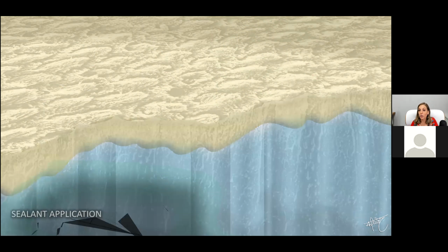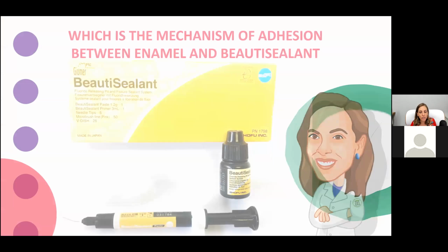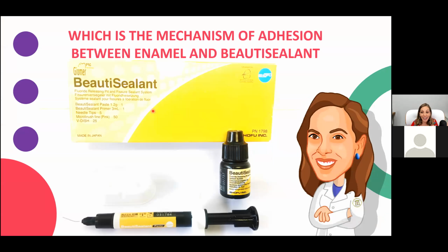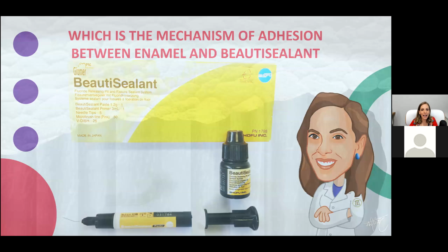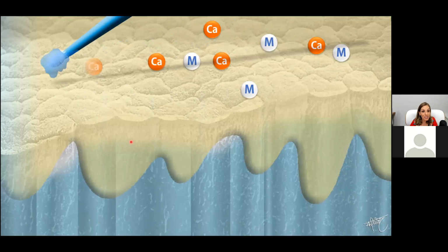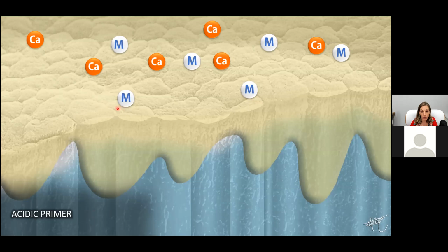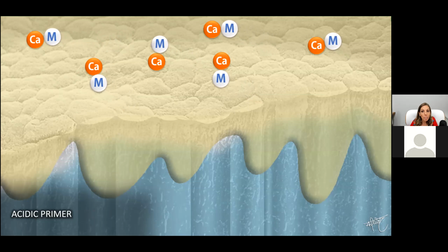And again, you are asking me, which is the mechanism of adhesion between enamel and BeautiSealant? And this was the question that I made to Mr. Giomer. And then he explained to me. Onto the enamel, when you apply the self-etching primer, this primer presents acidic monomers that will expose calcium, okay? And when this calcium is exposed, this monomer binds to the calcium. So there is a chemical adhesion between the monomer of the material and the calcium of the enamel. So this is the mechanism of adhesion.